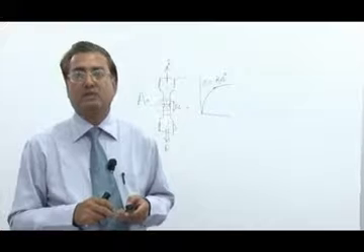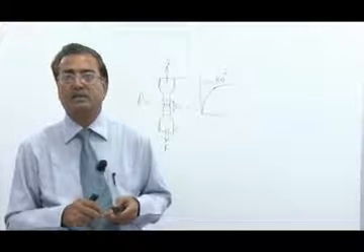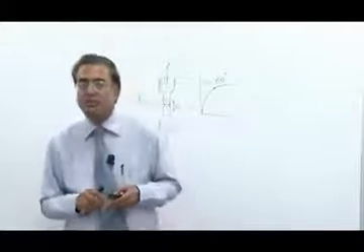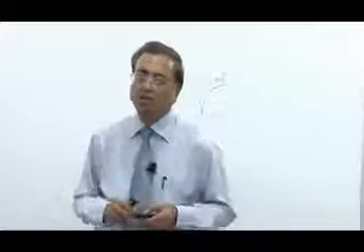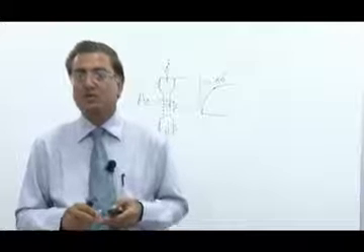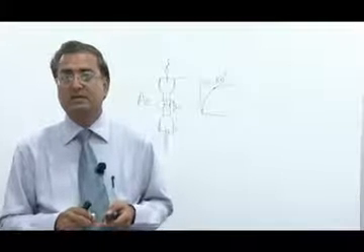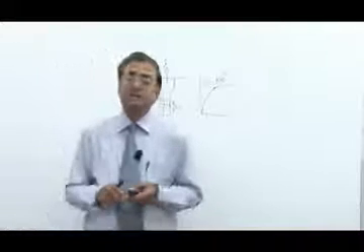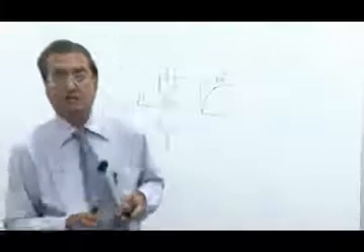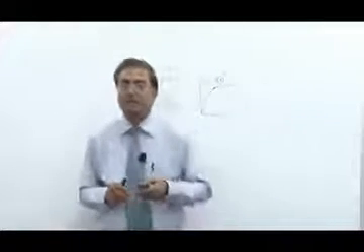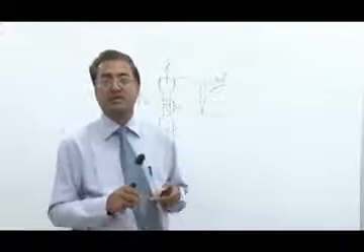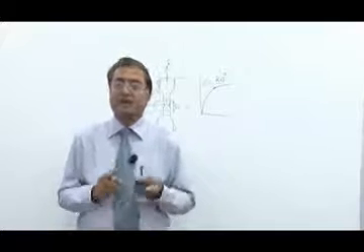So what happens at the maximum load point C? If you take the tangent, it will cut at point A, and from the 0 point, that becomes 1 on the strain axis, so 1 plus e, and wherever it cuts the stress axis, that will give you the ultimate strength. Then by substituting in the necking criteria earlier, a simple relationship for the true uniform strain can be found, which is equal to n.